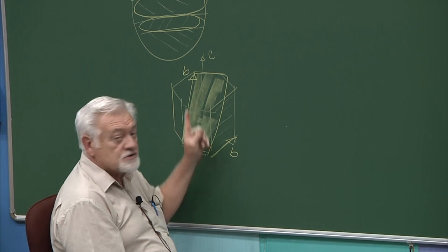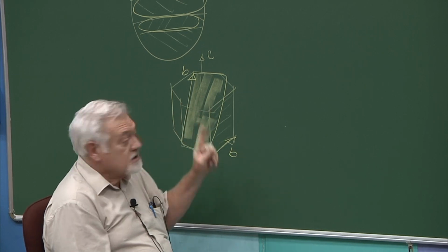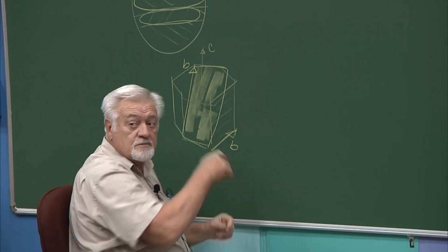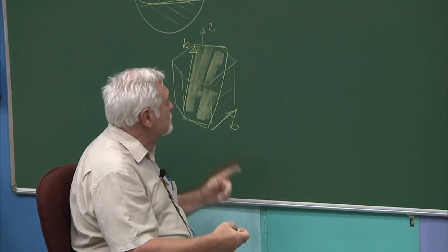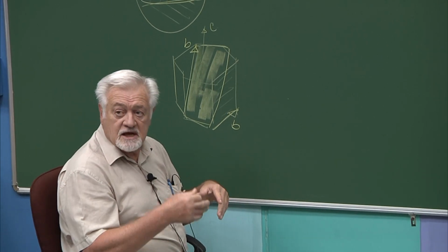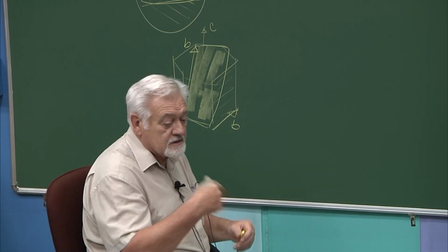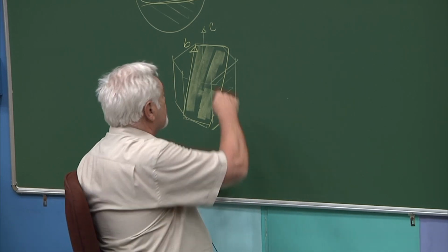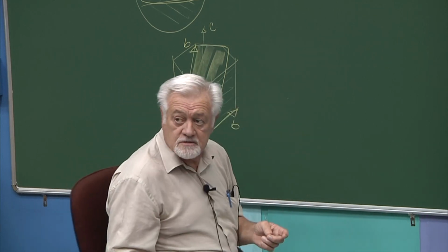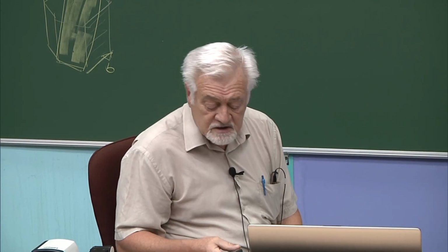provides deformation along the z-axis, but only in tension, not in compression. But that is why we have the pyramidal system that can provide both in tension and compression. But the compression twin will provide deformation in compression. But you can already see that the yield surface is going to be anisotropic, because things are going to be different in tension and compression.